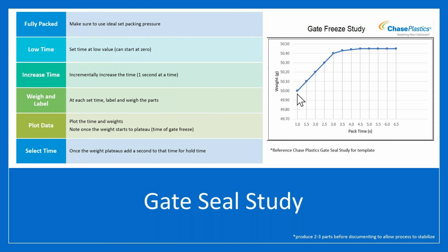We're going to plot that part weight as a function of packing time. And what we should see is an increase in weight until an asymptotic point where we're no longer able to pack more material into the cavity. This is a very good indication that our gate has frozen, and at that time, we can no longer affect what's in the tool with the screw and through packing and holding pressure. At that point in time, we might want to give a small buffer for material variation, and then we're going to use that as our packing time. So our freeze time plus a small buffer, and we're going to then set that as our packing time. That's going to ensure that every cycle we freeze the gate and that we have a consistent amount of material that stays in the cavity.